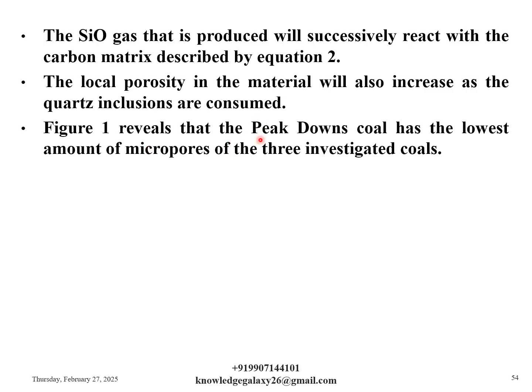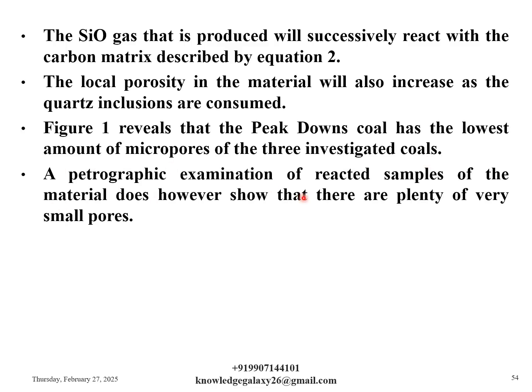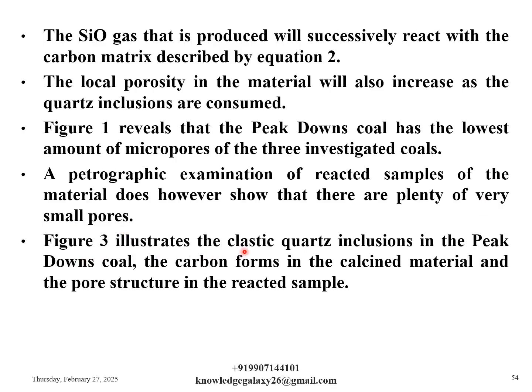Figure 1 reveals that the Peak Downs coal has the lowest amount of micropores of the 3 investigated coals. A petrographic examination of reacted samples of the material does, however, show that there are plenty of very small pores. Figure 3 illustrates the clastic quartz inclusions in the Peak Downs coal, the carbon forms in the calcined material, and the pore structure in the reacted sample. The figure is presented in the next slide.